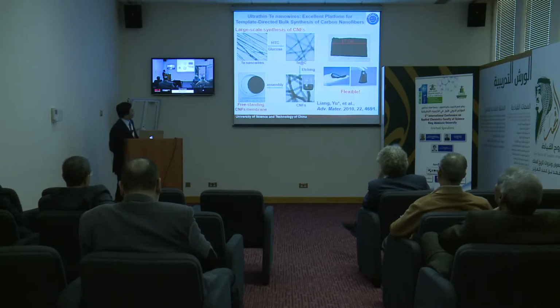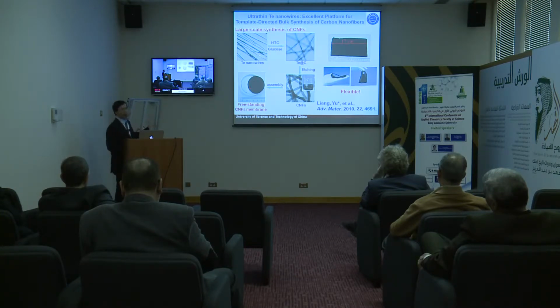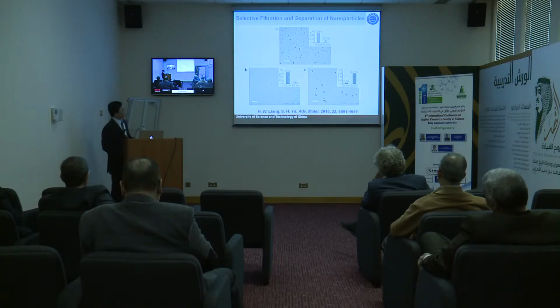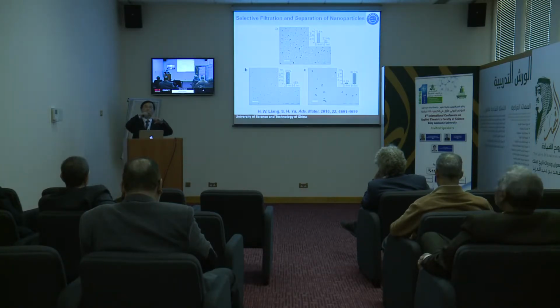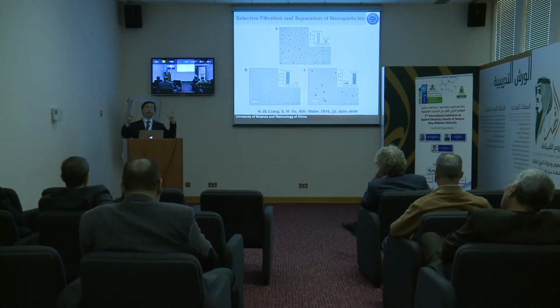So one application of our carbon nanofibers is this: if you remove the tellurium nanowire, you see black stuff here. If you remove it by etching, then you can get a carbon fiber. You can cast them into a membrane. This membrane is of macroscopic size and quite flexible, and because these fibers have different diameters, you can get membranes with different porosity.